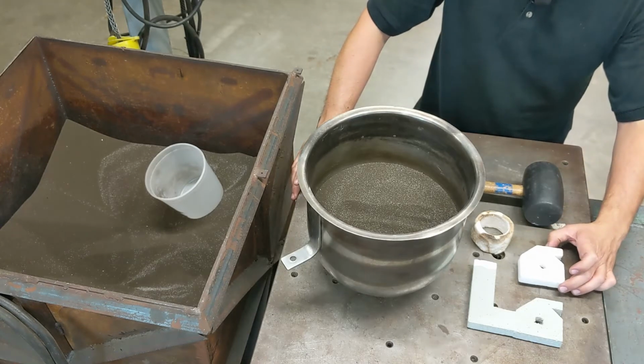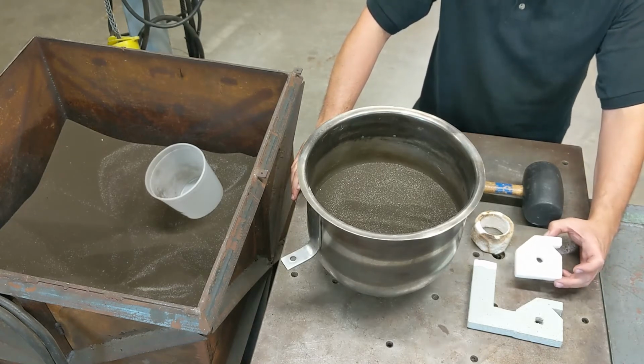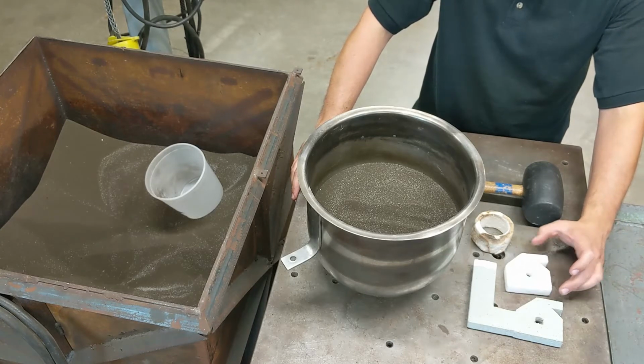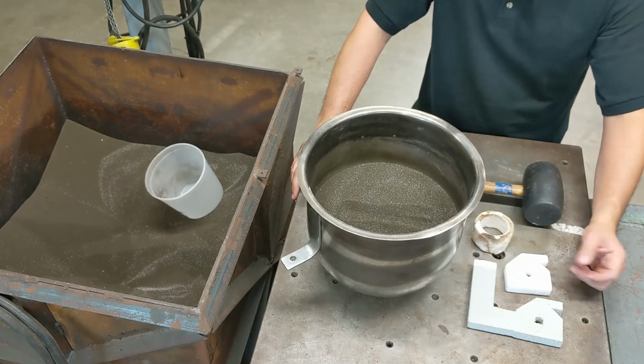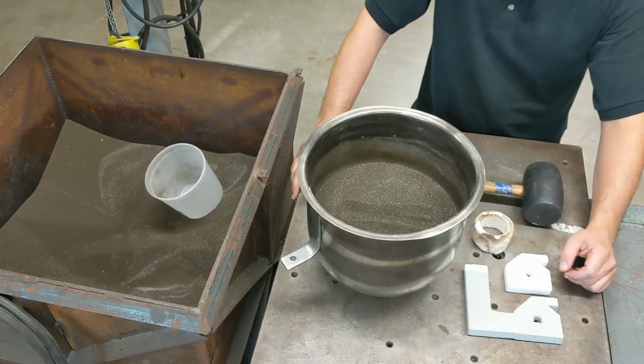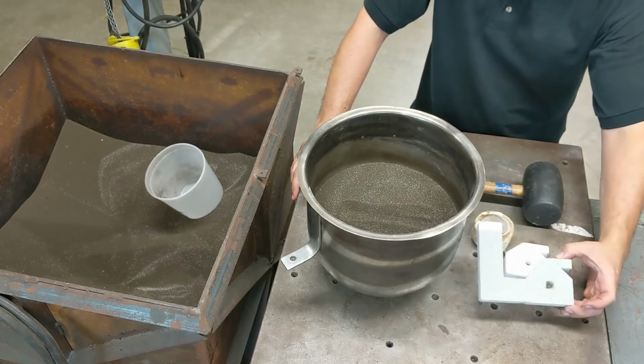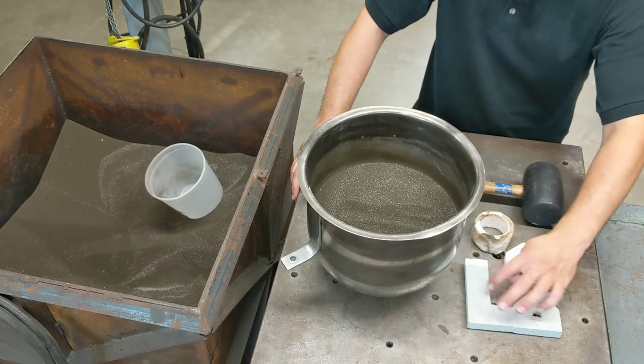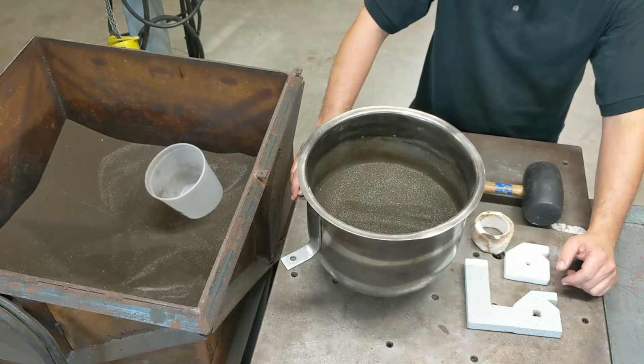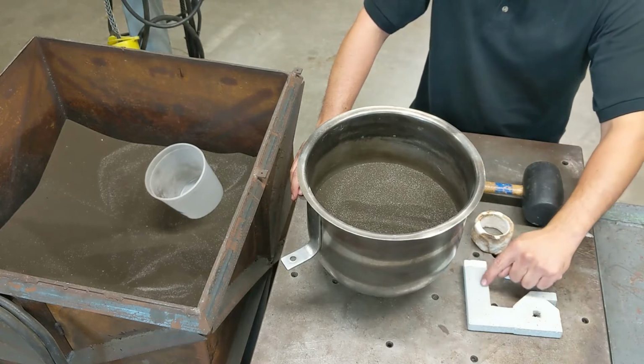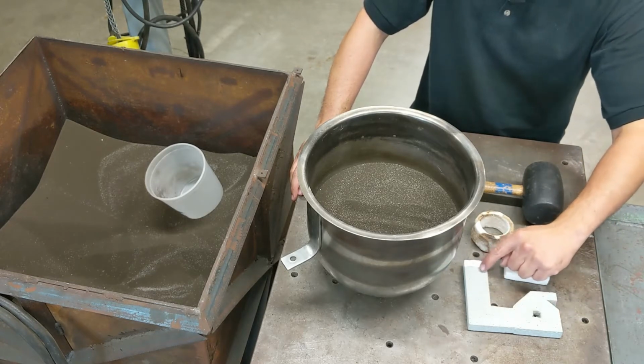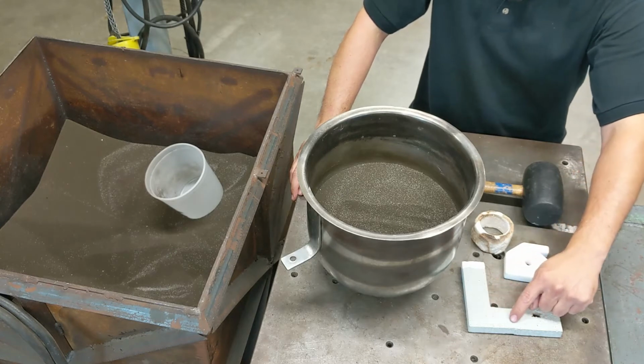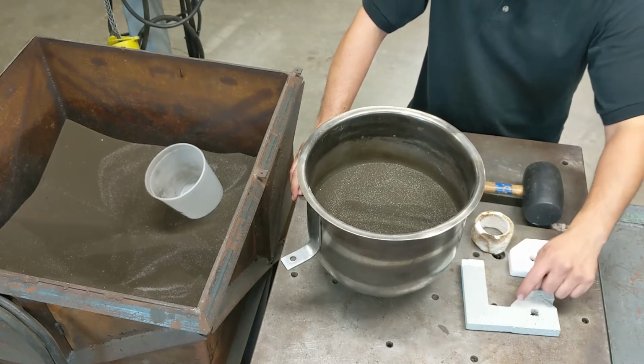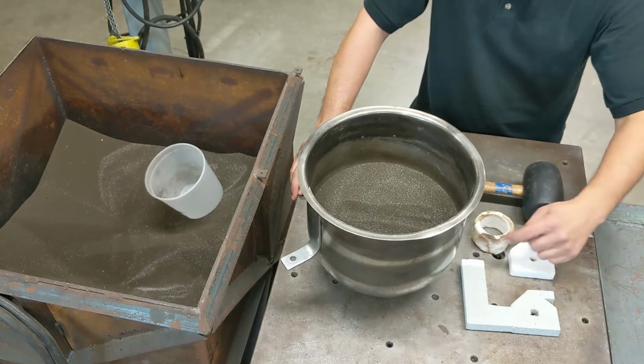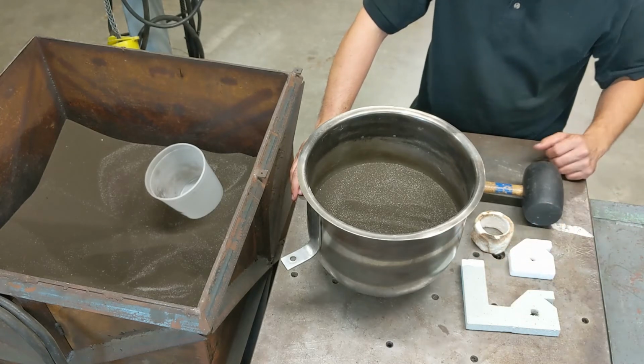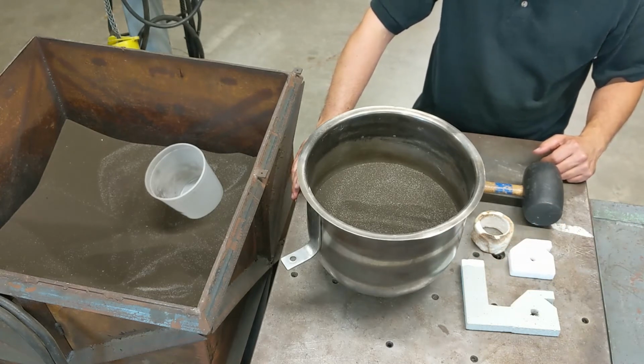The part that we're going to make here is a very simple 2D shape that I have cut out of polystyrene foam. When it's assembled and coated, it looks like this. So this has a refractory coating on it, which helps improve the surface finish. And I've added a gate and runner system. So I have a sprue here, a runner, and a gate where metal will enter the part and fill it. And the molten metal will vaporize this polystyrene foam as it goes.